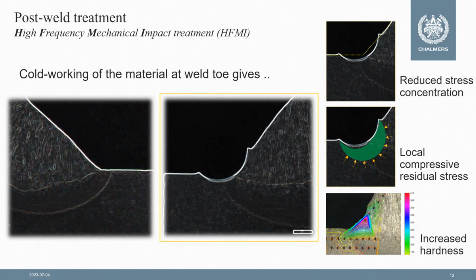The second, much more interesting and important effect is that this cold working and plastic deformation result in local high compressive residual stress, which is very important for the fatigue performance. From the as-welded situation, in which we usually have tensile residual stress, we now have compressive residual stresses, which are beneficial. And the third effect is that, due to the cold working and plastic deformation, we have increased hardness and increased local yield strength of the material in the region which is critical from the point of view of fatigue.